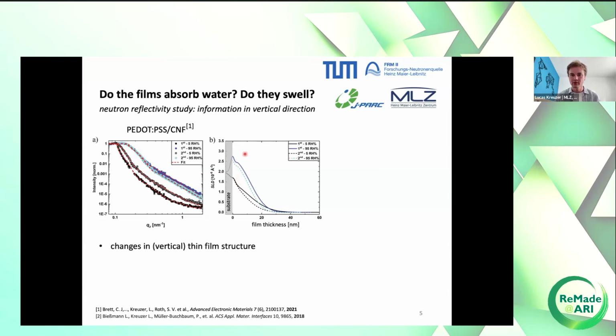In this case, we use D2O, so heavy water, because it has a very high SLD. It gives us a better scattering contrast. And this increase in SLD is D2O moving into the film. And this happens especially close to the substrate, because here the difference in SLD is the highest, and then it somehow fades out. This is the first thing.